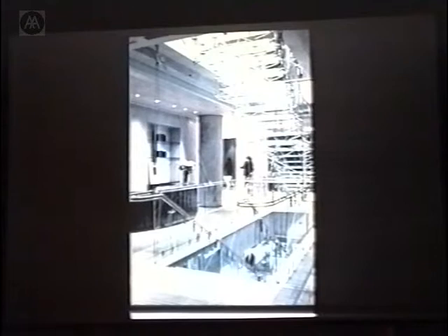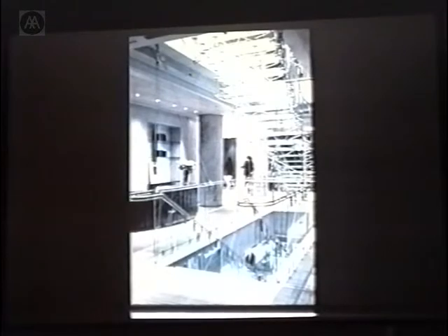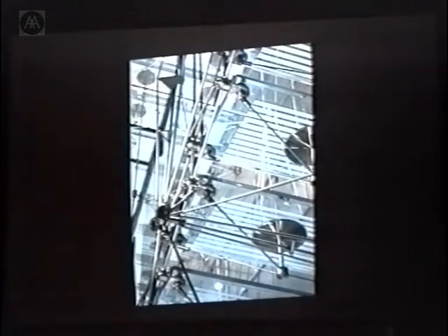And I think this was there for about, this was 1990, so it's probably there about 8 years or so. And I heard of one cracked tread during that period, so it's quite interesting that it can work, be robust, and be very serviceable, and obviously very elegant. There's the detail close up. You can see the acrylic, and it's quite nice here because the glass has that beautiful green edge, and then you have the clear acrylic underneath. I think most of Eva's staircases use this method very successfully.